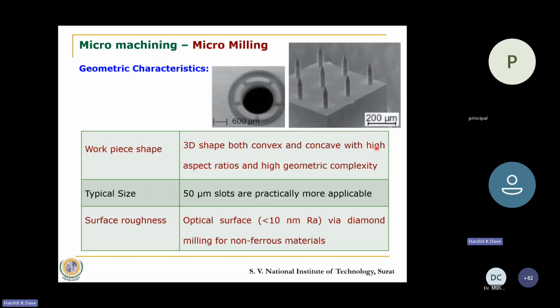If we try to compare the geometric characteristics, here we can make convex as well as concave surfaces. In case of turning, only 3D convex surfaces are possible, whereas in case of micro milling, 3D convex as well as concave shapes with high aspect ratios and very high geometric complexities are possible. As small as 50 micron size of slots are practically applicable. There are features where you create slots as small as 50 microns. So if the slot width is 50 microns, it means your end mill cutter will also have a 50 micron diameter. Similarly, the surface roughness on certain aluminum components has been observed to be less than 10 nanometers. That has been reported. So there is a possibility to generate a mirror surface image on certain non-ferrous alloys like aluminum.